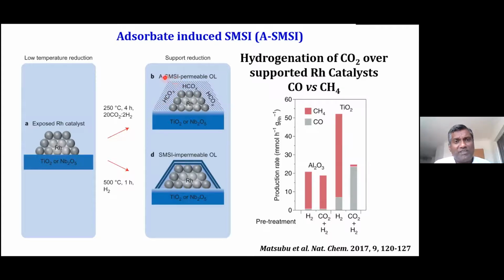So that's what they called adsorbate-induced SMSI. This permeable monolayer is porous, so the small molecules can enter into it and access the metal nanoparticle. Consequently, what they got was more or less exclusively CO selectivity. The selectivity for CO is much higher because of this adsorbate-induced SMSI. So this is another kind of strong metal support interaction.